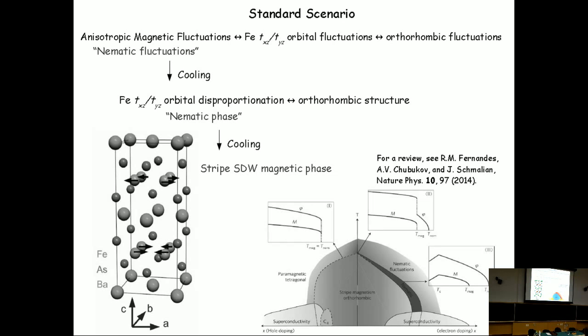So this regime is called the nematic regime, where the magnetism is isotropic, but the structure and also the electronic conduction is still anisotropic. And it was realized later that above this nematic phase there are still some sort of fluctuations that can be observed by Raman scattering, which I'm going to show you later. It's a very interesting regime where you have this kind of mysterious electronic fluctuations that permeates the response of the system. And for sufficiently high doping, you see the superconductivity dome over here, which resembles somewhat the phase diagram of the cuprates. So this system has attracted a lot of interest because some people think that we can understand the cuprates better if we proceed in the research of this system.